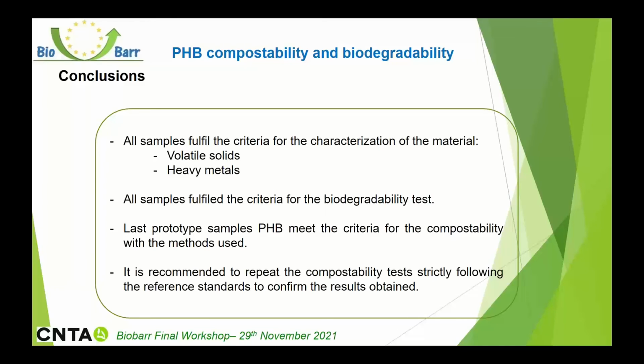As conclusions, all tested prototypes can be considered safe from a chemical point of view. All tested prototypes have been biodegradable. And finally, the last 3 prototypes based on PHB with different treatments, Alox, metallized, and multilayer PHB PLA, will be the polymeric prototypes which fulfill all the technical criteria for being considered biodegradable and have the capacity to be compostable.